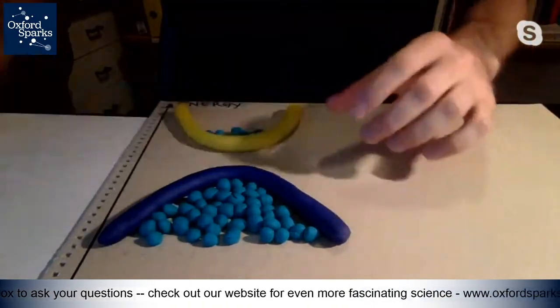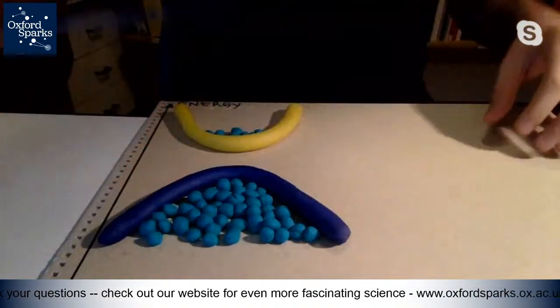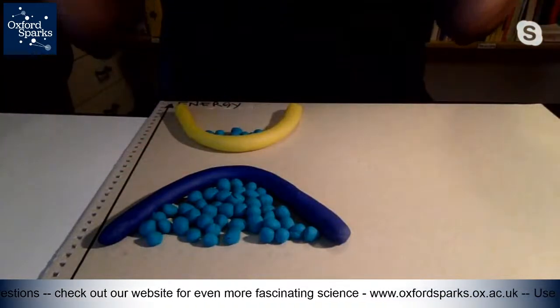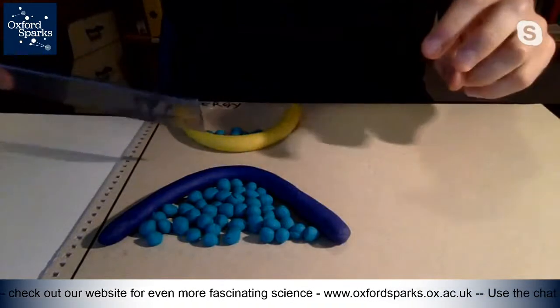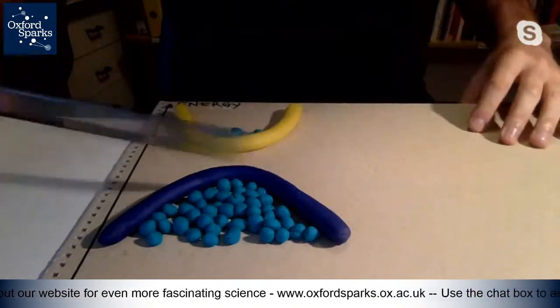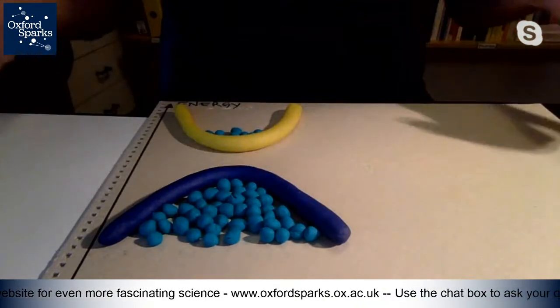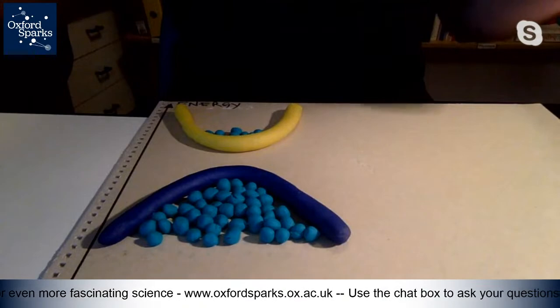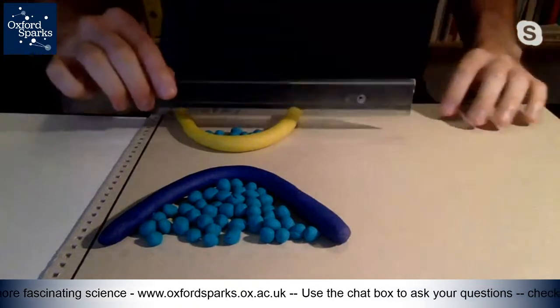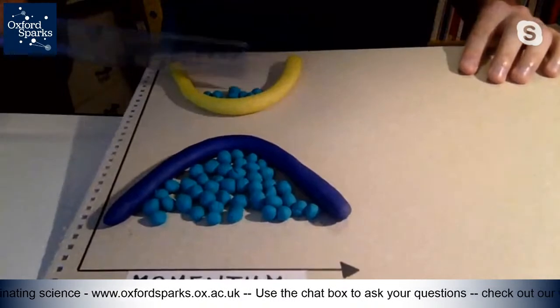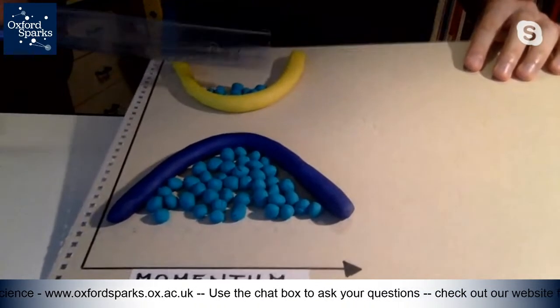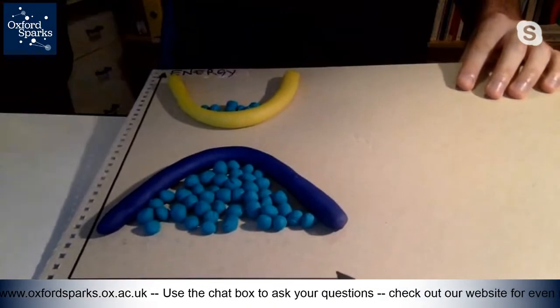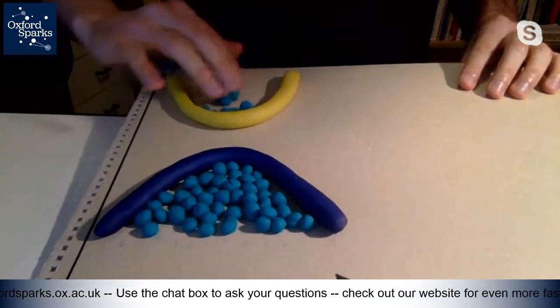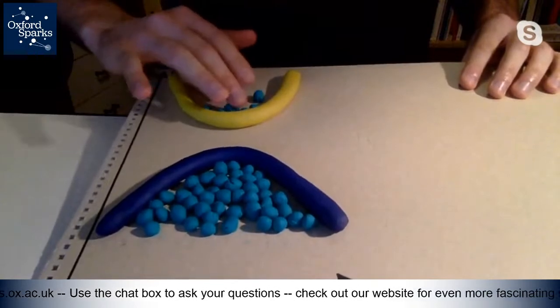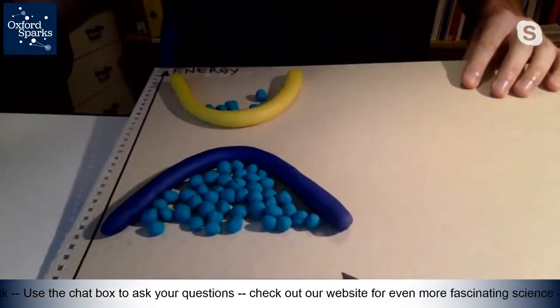So another thing is that these bands are separated from each other by this band gap. And this is a so-called forbidden band. And here, no electron can live. So we can only populate this lower band or the upper band. So what happens if we have our Fermi level, so our maximum energy, somewhere here, where the upper balls are located? Then it means that this area is empty and the electrons can kind of move freely around. So this is actually what causes electrons to conduct, because they can move around very easily.